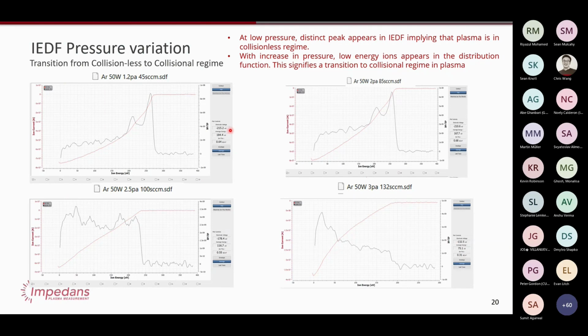So in this case, the electrode is at minus 215 eV on average. So that'll be the sort of average energy that the ions see, pretty much. Although in this case, the actual measurement of average energy is lower because the collisions are pushing it lower. So these ion energy analyzers can also measure what this DC self-bias is as a function of different conditions, which can also be important.